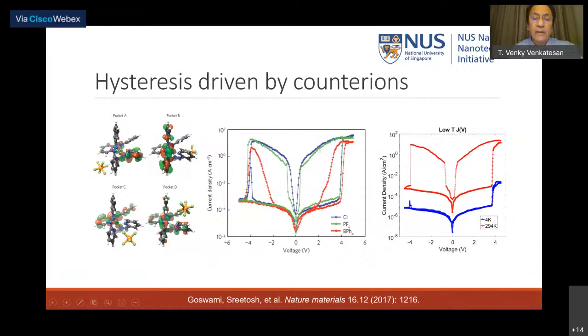Okay, so for example, if I now change the counter ion from a light counter ion like chlorine to boron with a 4-phenyl group attached to it, which is a very heavy counter ion, you can clearly see the hysteresis become very sluggish. So this tells you something to do with the inertia of the counter ion. So these are the tools with which you can actually control the property of this molecule.